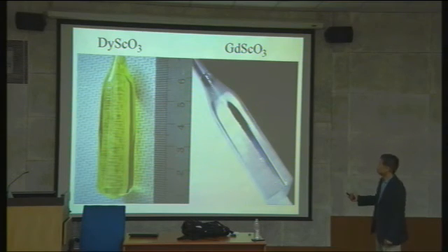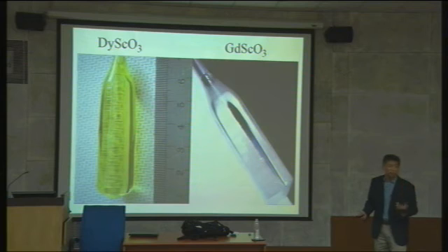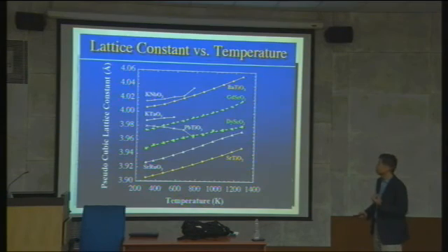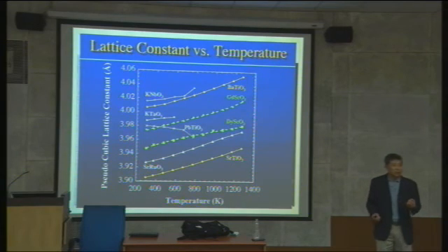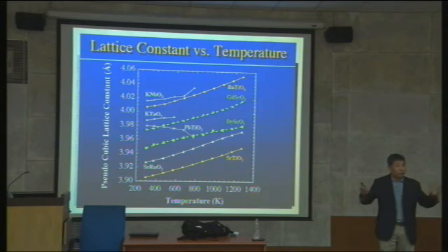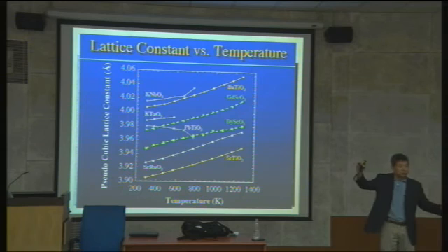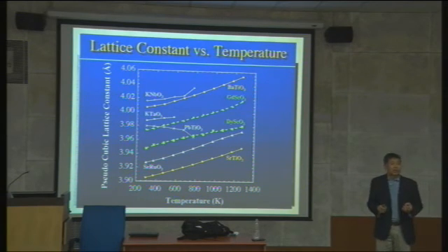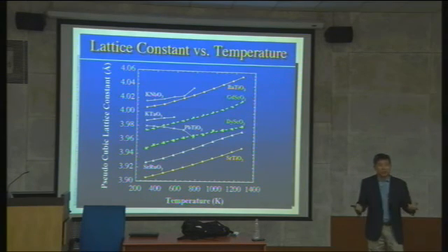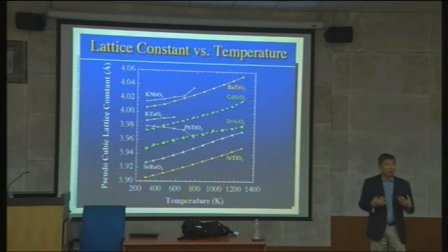So for growing this one, Czochralski grown single crystal, orientation measurement, cutting the crystal substrate, and then you grow the thin films. And then you have to measure the lattice parameters very carefully as a function of temperature, because we want to know the real lattice parameter at growth temperature, down to low temperature. You actually study this. So it's not just growing the material and that's it. We trust it? I think you have to prove it. You have to measure your own.